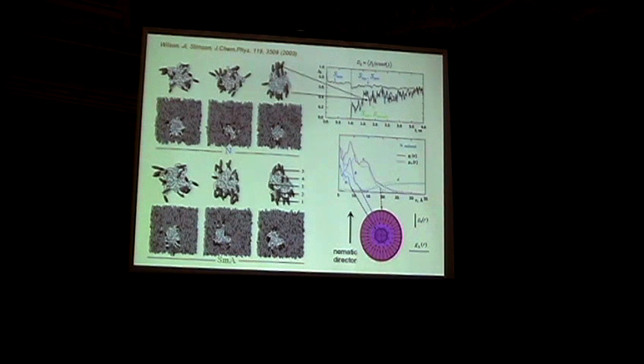Also what we found is that in the smectic phase, this tendency is less because it is energetically more favorable for some molecules to find the closest, nearest smectic layer. And so the mesogens are not anymore separated at the poles of the molecule.